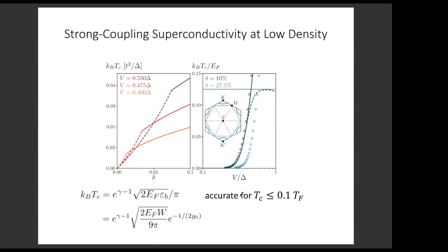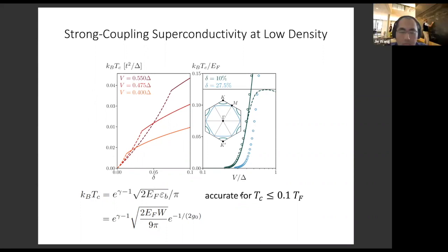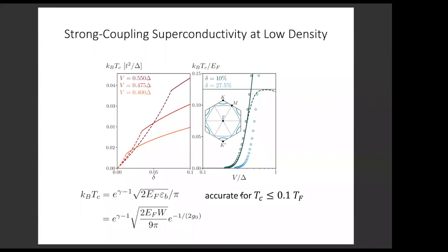So in the low density regime, but not too low density, we are still in the BCS regime. And then this is the expression for k_B T_C, and it's proportional to the square root of the Fermi energy and the binding energy, the 2-particle binding energy. And if we express it in terms of the microscopic parameters, it's shown here. This formula is accurate from the Monte Carlo result. It is known that this formula is quantitatively accurate even when T_C reaches 10% of T_F. So what I've done is basically show that starting from a repulsive model on the lattice, we can actually get strong coupling superconductivity. Okay, so next slide.